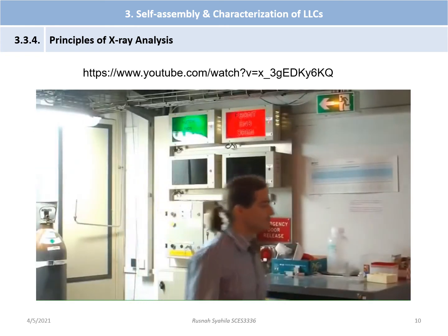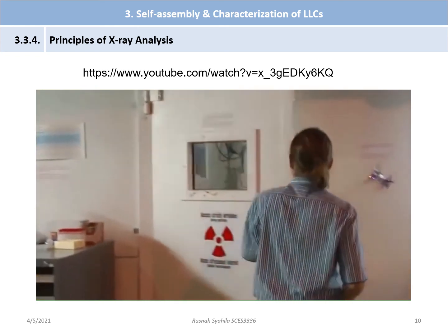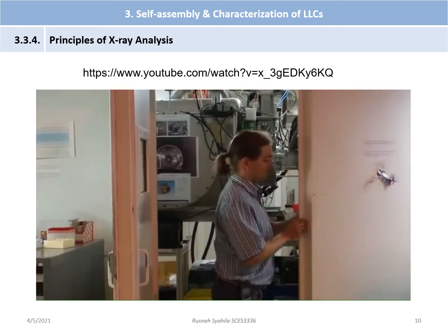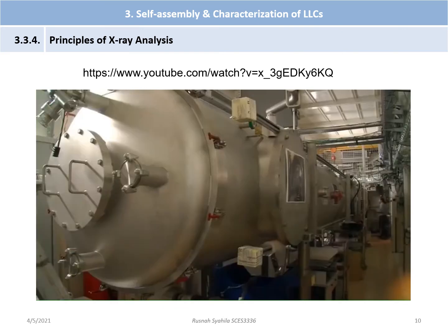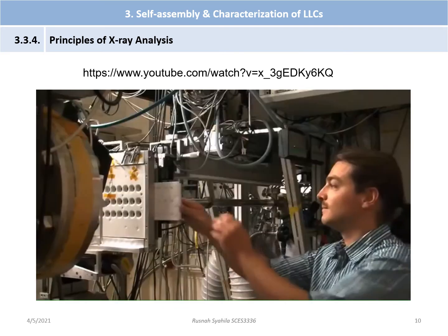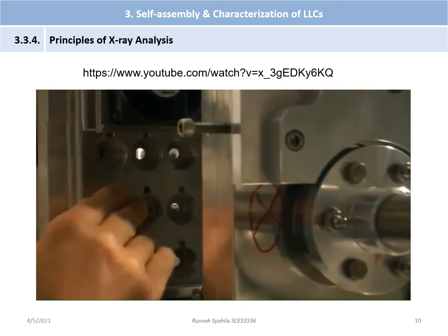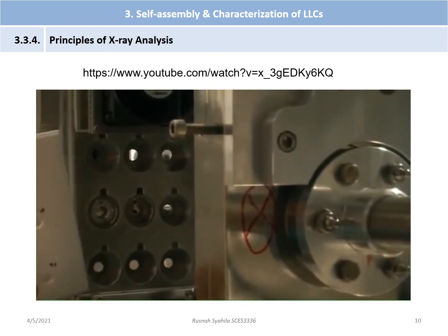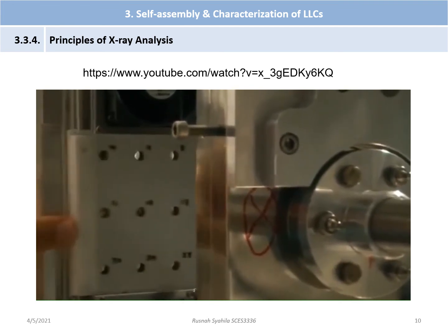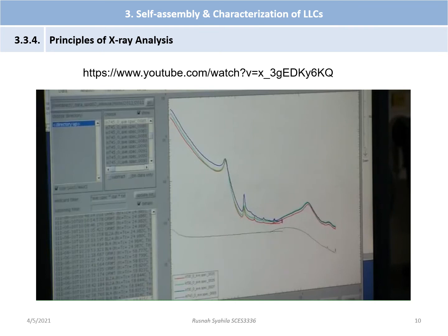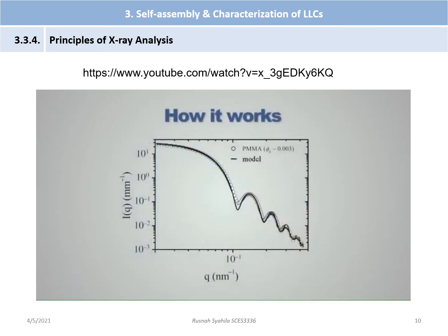As samples can serve, for example, polymer pieces of a few millimeter size, a drop of gel, or also solutions from 15 microliters. The scattered intensity recorded in the 2D detector is first azimuthally averaged, and the scattered intensity in absolute units as a function of the scattering angle can be afterwards fitted to structural models, which helps to distinguish between different morphologies, for example, spheres, micelles, or vesicles.